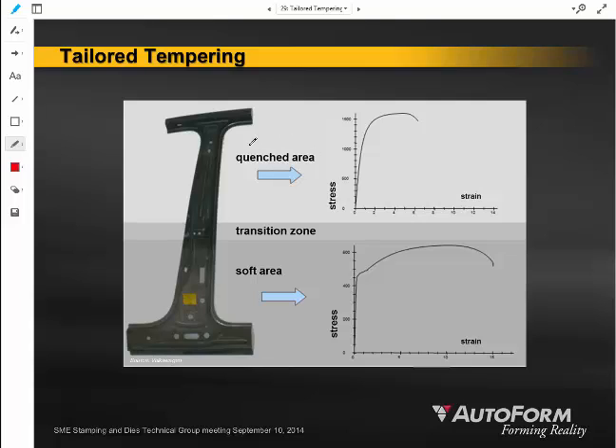So in this case, the B-pillar, they quenched the B-pillar at the top. That's going to form a lot of that martensite microstructure. That's going to be the strongest, highest strength material that this B-pillar is ever going to see. Then there's going to be a little bit of a transition zone to the material that is allowed to cool or quench slowly. So the die at the bottom portion of this B-pillar is being maintained at around 400 degrees Celsius. And by holding that die warmer during the forming operation, we ensure that its microstructure is different than the top half, which is being cooled to 80 degrees Celsius.